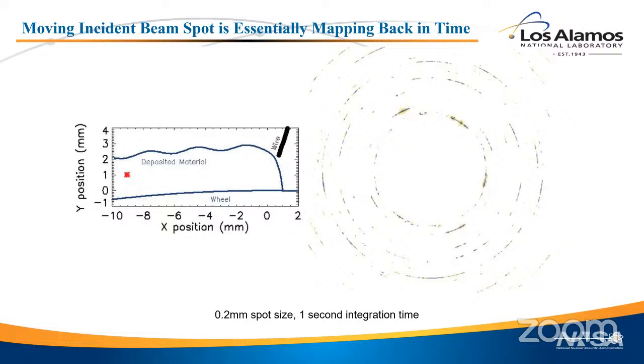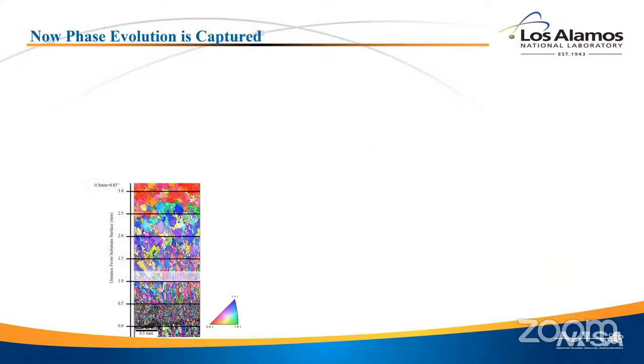So we can see the phase transformation from liquid to solid. It happened too quick for you to see in the movie, but you can see the change from ferrite to austenite. You can see the texture evolve. We can see the stress develop. Those are all microstructural features that we pull out of the data that you just saw there. So this is more normal EBSD that you would see. This is a section of that line of metal that we laid down, and the white shading on that line is where our X-ray beam was penetrating when we laid this material down. So that's our integration volume.